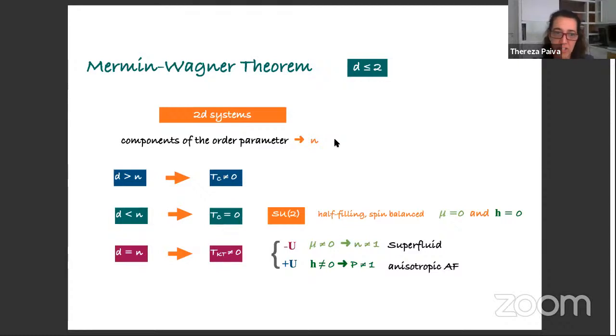So what's the question? So if you have D, the number of components in your order parameter, equal to the dimensionality of your system, then you have a Kosterlitz-Thouless transition at a non-zero temperature. And okay, this is not the case when we have the balanced system or at half filling, where we have SU(2) symmetry. But when we dope the attractive system and we break the degeneracy between superfluid and CDW, then this happens, or in the anisotropic antiferromagnetism, when we have canted spins, the Z direction correlation functions are actually different and have more energy than the XY correlation functions, then also we have a Kosterlitz-Thouless transition.